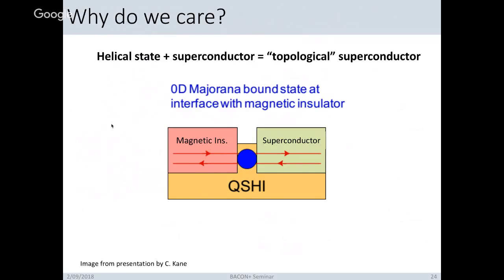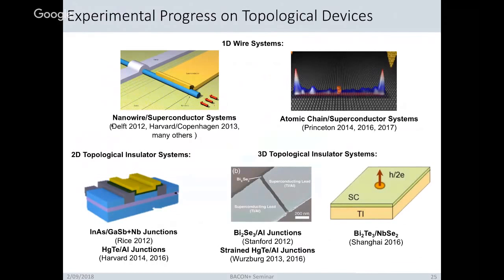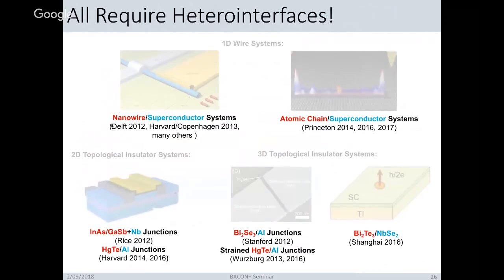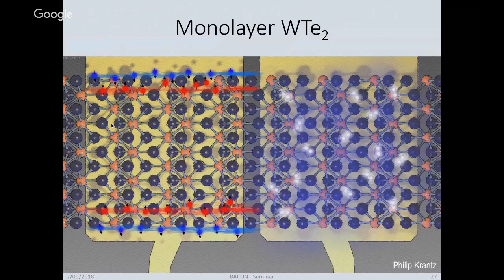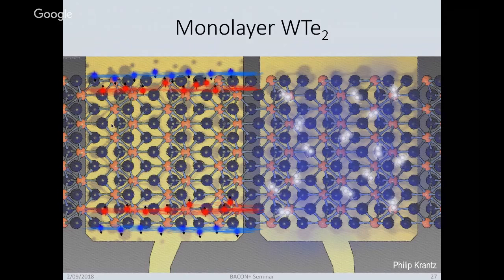Now, that's already interesting, and there's more predicted that occur beyond that. If you would have managed to take this helical mode and contact it with a superconductor on one side, and find another way to gap it out, some different kind of gap than a superconducting gap opposite it, you can create a Majorana bound state in principle at that interface. And this is a subject of intense investigation, with all methods of creating helical modes, from nanowires to 3D topological insulators, as well as other 2D topological insulator platforms. And so far, to my knowledge, especially with gate-tunable structures, you have always had to have this situation where you have one material providing a helical state, here in red, and a different material providing a superconducting phase, in blue. And what hasn't been managed is to find a situation where we can have both of them in the same material, and hopefully not have to deal with this interface issue that results from having to deposit or sputter, clean these interfaces up, or whatnot. So coming back to this picture from earlier in my talk, I hope to convince you that we have seen both the 2D topological insulator phase at low doping, and then the superconducting phase at slightly higher doping, but accessible by electrostatic gate electrodes.